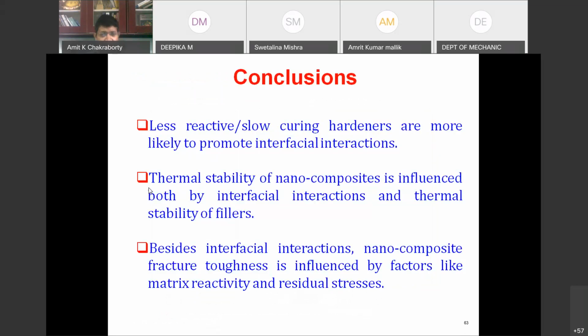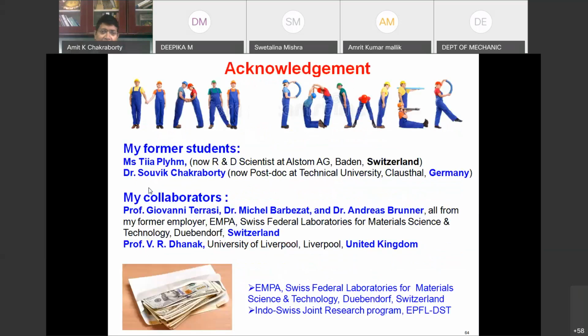So, in short, the conclusion that we have found out in both the studies is that even if you modify the filler, even if you start with an extremely good filler having extremely good mechanical properties, there is no guarantee that experimentally the property of the composite material will be enhanced unless you are very careful in looking at the details of how fast they are curing, how well dispersed the system is, how the particles are well dispersed, how stable the dispersion is, etc.